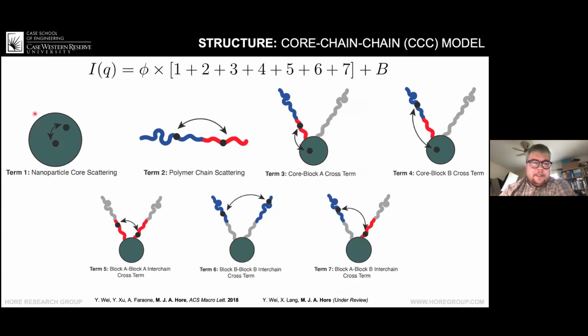And the scattering consists of terms that are just scattering from atoms in the core, just from scattering in the grafted chains themselves. And then there are cross terms between the core and the different blocks of the polymer. So the core in the inner region, the core in the outer region. And then you also have corresponding correlation terms between the polymer chains themselves. So you end up with a function that has these 7 terms. But what I want to emphasize is there's maybe 2 at most free parameters that we're fitting here. So it's a really well-defined model, and then we analyze our scattering this way.